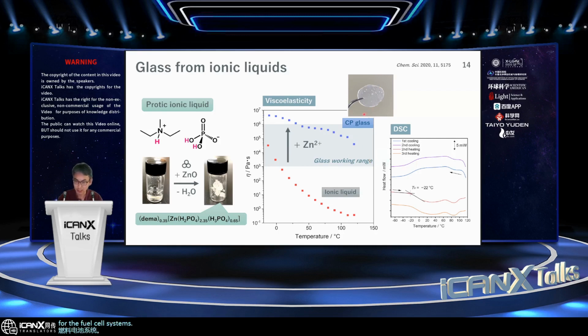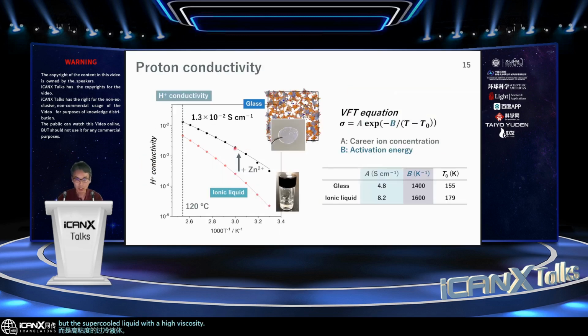By the way, this kind of compound shows a glass transition at negative 22 degrees C. So actually this temperature regime is not the glass, but the supercooled liquid with high viscosity. And one interesting thing is that this obtained glass shows very high proton conductivity as shown here, which is much higher than the pristine ionic liquid. So this is the starting ionic liquid composed of ammonium cation and phosphates.